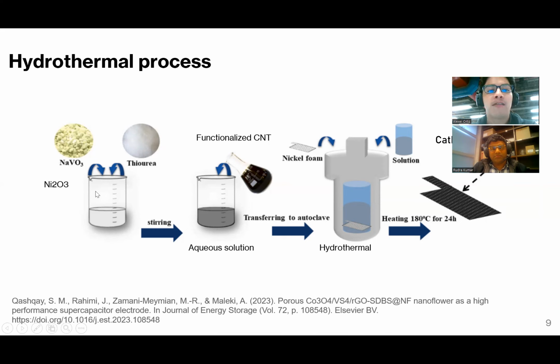Well, we're going to stir it in the solution. We are going to add the functional carbon nanotubes. Here we use functional carbon nanotubes because normal carbon nanotubes don't have the functional groups to react with the components, so they cannot be attached to it. So we first have to functionalize the CNT with some functional group like a hydroxide or something like that, so we can add it to the solution and it can stick to the CNTs.